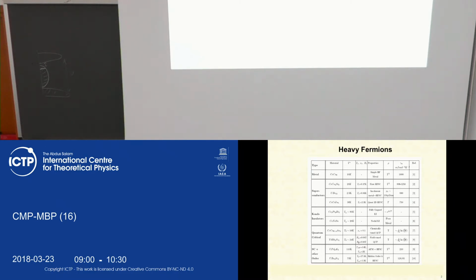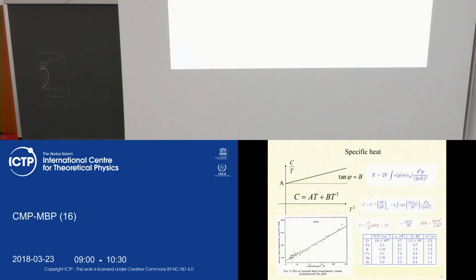Therefore, if one compares the Fermi energy and the critical temperature of superconductivity, one can see that there is something like a factor of 10 between them, which allows us to say that these compounds are true high temperature superconductors, not in the absolute sense of being above nitrogen temperature. No, measured in units of Fermi energy, this is a really very high temperature of superconducting transition. So the puzzle is where these heavy masses come from, and maybe understanding the mechanism of formation of heavy masses would help us also to understand the mechanism of high temperature superconductivity.